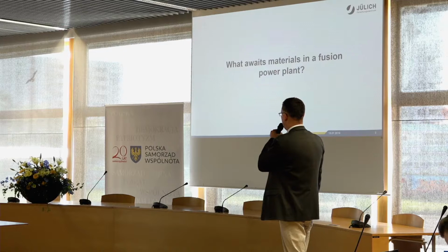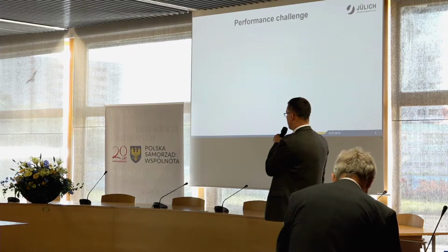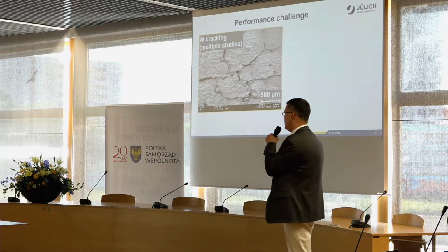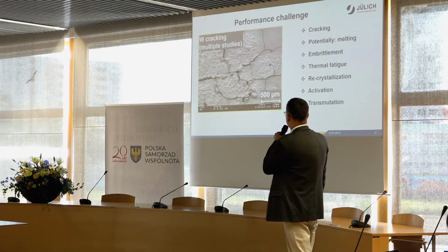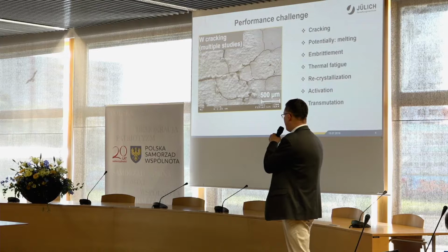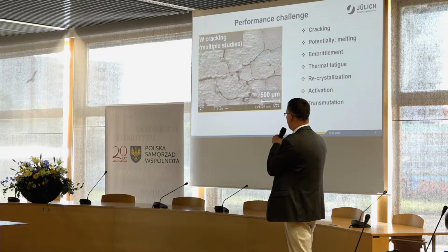From the performance point of view, during regular plasma operation, we have quite a lot of experience from present-day machines. You can see all these effects, and there are quite a lot of them. We could, in principle, have lectures on any of such events reducing the damage of the materials. And we can add a couple more to what is already mentioned, like embrittlement during neutron irradiation, thermal fatigue because of the cyclical loads, recrystallization while going to high temperature, and in addition, activation and transmutation because of the much higher neutron fluences which are going to happen in the fusion power plant. This is half of the problem, I would say.